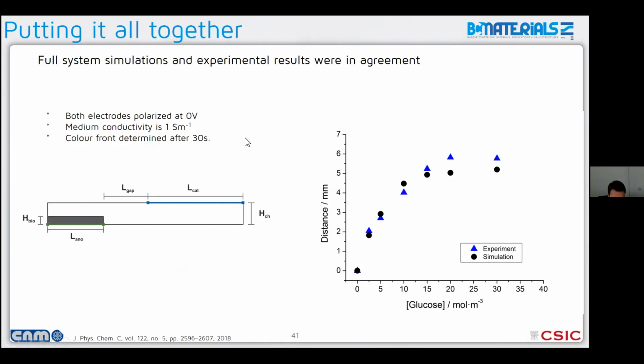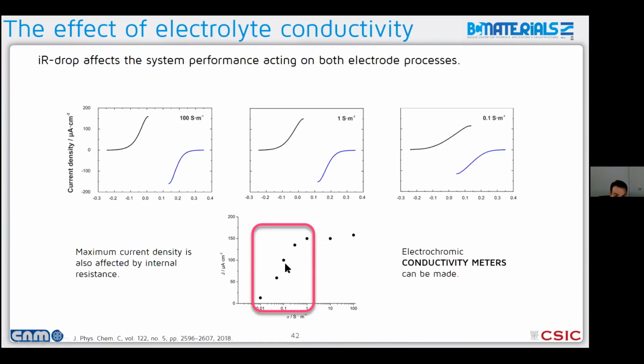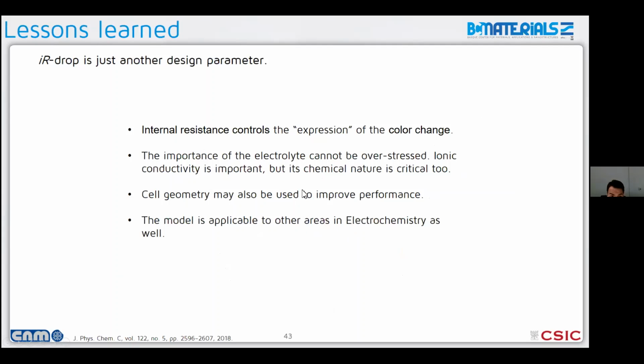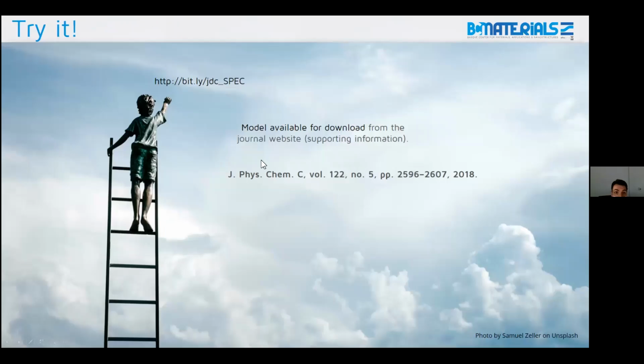at conductivity values in the range of 1 Siemens per meter, which is close to, I think, 0.1 molar KCl, if I remember correctly. So around here. So what we saw is that if you change the conductivity, you get different responses from your system. You see different current outputs, and you can actually use this also to make a visual conductivity meter, because by just looking at the color of your electrode, if you are in this working range, you can extrapolate the conductivity value. So it's quite interesting. So again, we can use internal resistance as a design parameter. The model, by the way, is available on the journal website as supplementary electronic material.